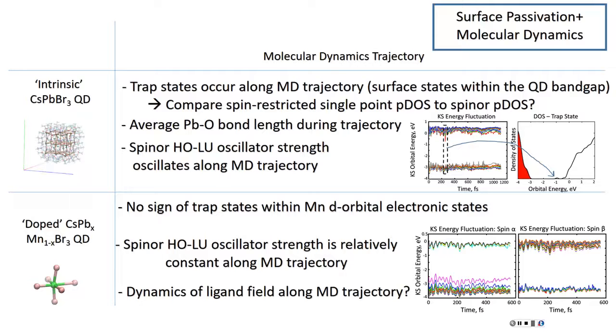So that's the intrinsic dot, and with the doped system, it's not as interesting. So we did spin polarized, so we have two different energy fluctuations. We have your spin alpha, where all the up spin states are from the manganese, and these two states here that are kind of separate from everything else are 3d states, or dehybridized or whatever. So they're from the manganese. And you can see that along the trajectory, there are no states that pop up in between them, so surface states don't affect there.